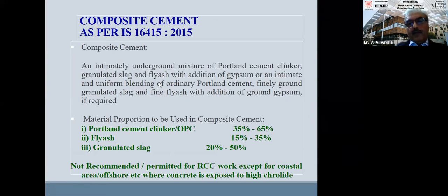But the issue here is that the Portland clinker content is 35 to 65%. The only problem being faced in this is that 35% content of OPC makes the cement less durable in terms of resistance to carbonation. That issue is being discussed in the BIS committees. So presently it is not recommended for use in RCC, but in PCC and road construction, you can easily use it. It's a green cement, very good cement otherwise. But for RCC work, it is yet to be permitted.